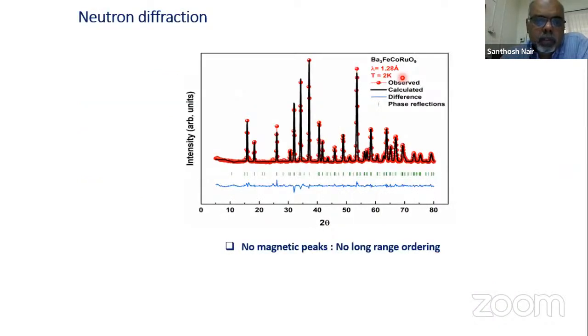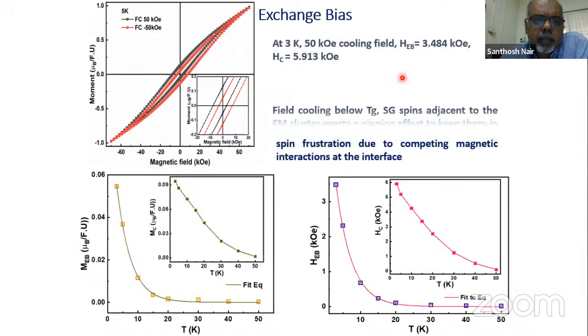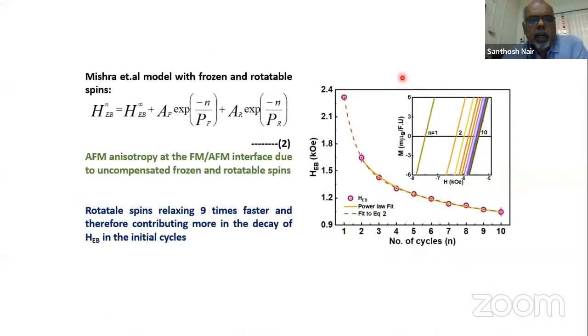We did neutron diffraction at ILL, and what it says is there is no long-range magnetic order at the lowest temperature or at any temperature. The statistics of this data are not exactly great, but I think the analysis is fairly good. So this also shows a glassy phase is involved, and we see similarly exchange bias, but not very high, 3.484 kilo-oersted, but we see exchange bias. I'll not go into that.